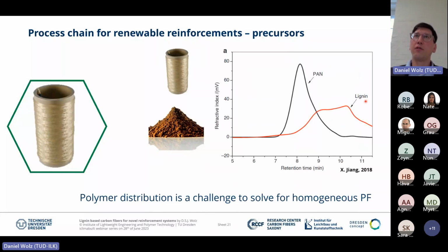Additionally, we have there the challenge. If you look at this gel permeation chromatography analysis, you see that we have there a very smooth distribution of polyacrylonitrile polymers, meaning that we are having less defective carbon fibers, smooth production. There is not very much difference. If you are looking at a raw material like lignin, this has much more broadening in the polymer distribution, meaning we have to be much more sensitive in preparation, fiber spinning, thermal conversion, up to application. So polymer distribution is still a challenge to solve for homogeneous precursor fibers to get nice carbon fibers.